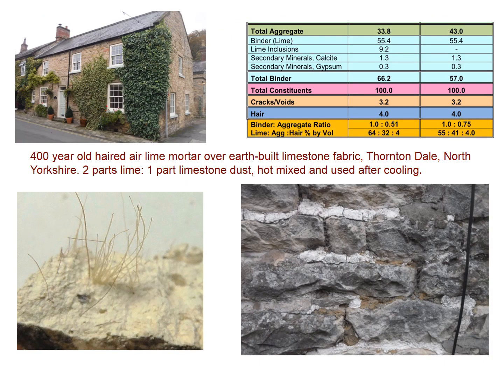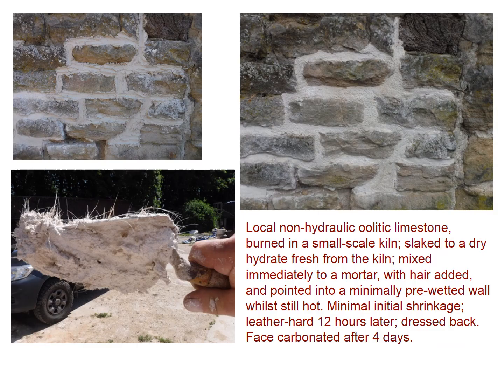Here in Thornton-le-Dale, where I'm talking to you from now, a 400-year-old hair-reinforced air lime mortar over earth-built limestone fabric: 2 parts lime, 1 part limestone dust, hot mixed and used a while after cooling. An attempt to reproduce a very similar mortar, this one without any addition of limestone. So local non-hydraulic oolitic limestone burned in a small scale kiln, slaked to a dry hydrate fresh from the kiln, mixed immediately while still hot, of course, to a mortar, hair added and pointed into a minimally pre-wetted wall while still hot. Barely any shrinkage initially, leather hard 12 hours later, and dressed back, and the face carbonated after 4 days.